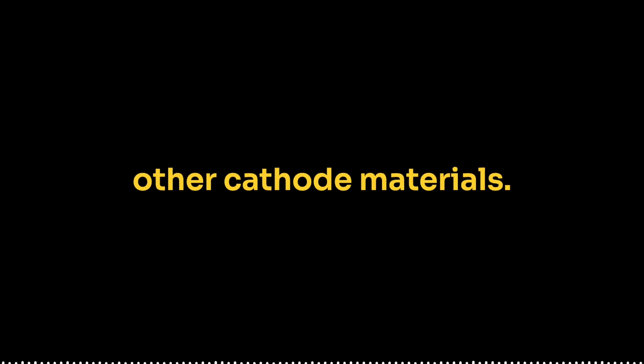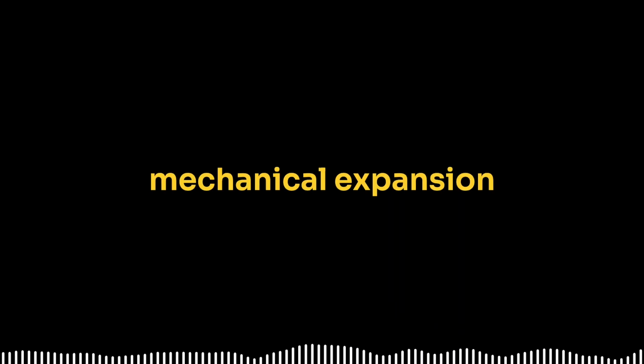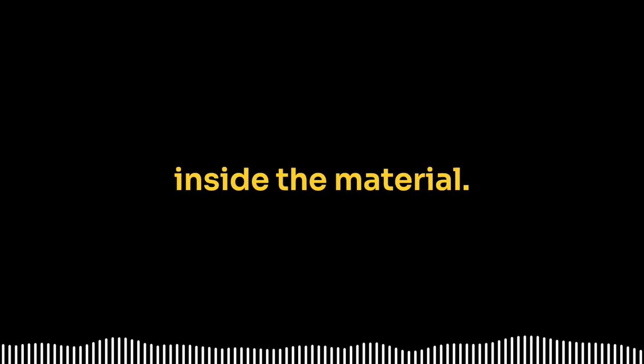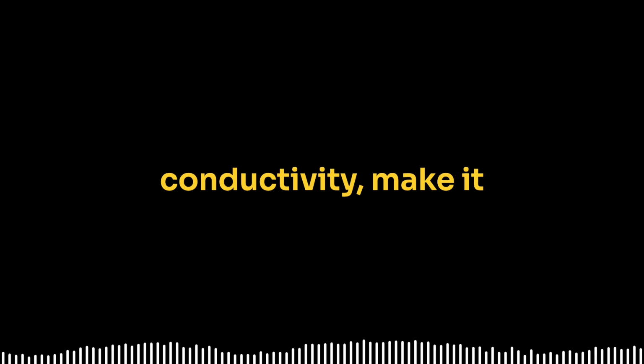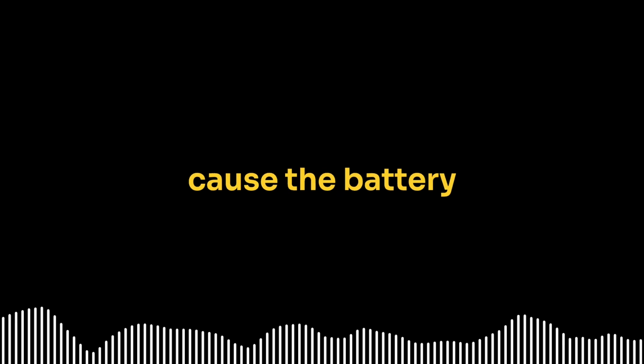cathode materials. As we discussed earlier, charging and discharging cause lithium ions to move in and out of the structure. Over time, this mechanical expansion and contraction can lead to microcracks forming inside the material. These cracks reduce conductivity, make it harder for lithium to diffuse, and eventually cause the battery to lose capacity.